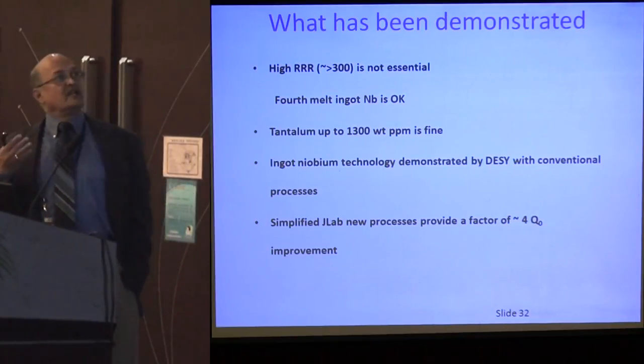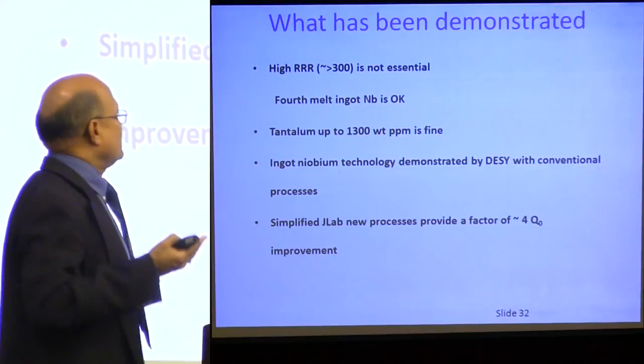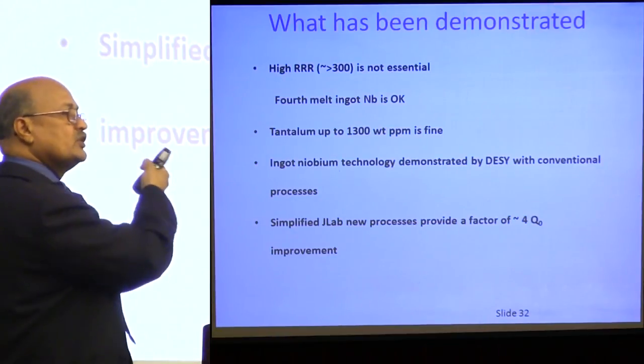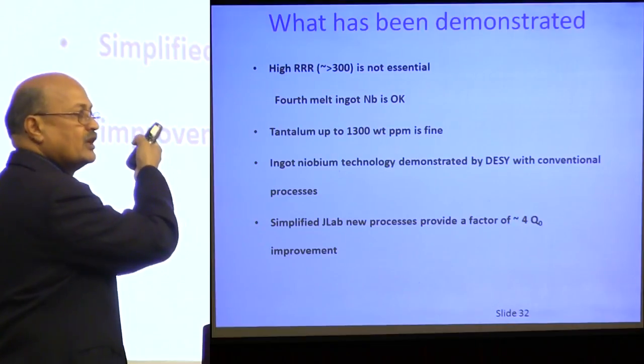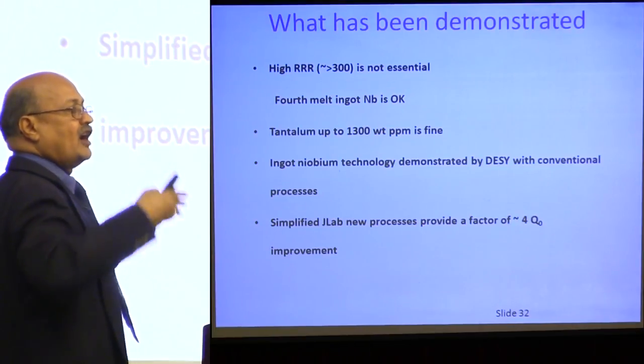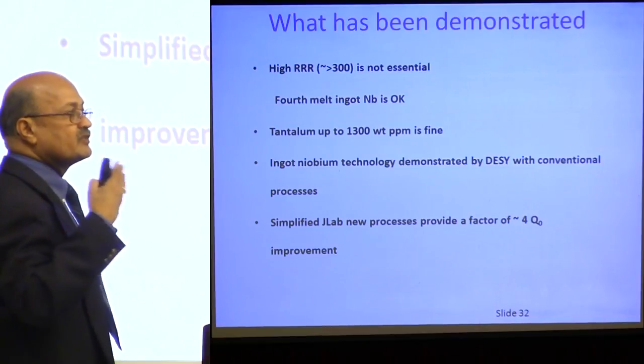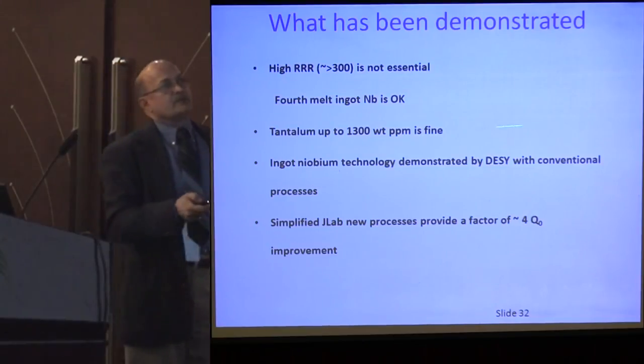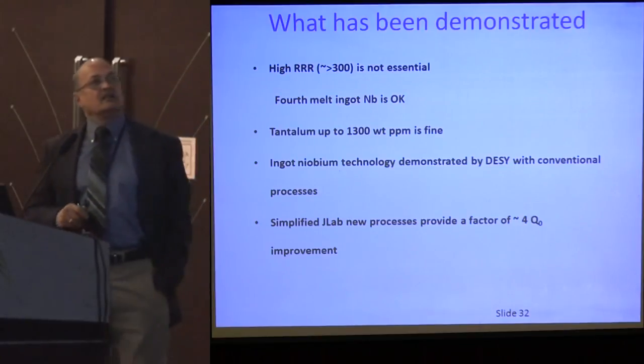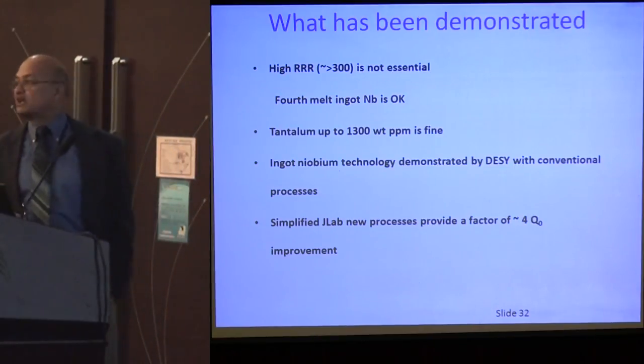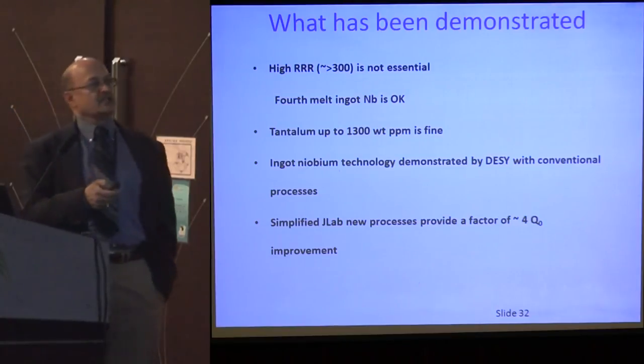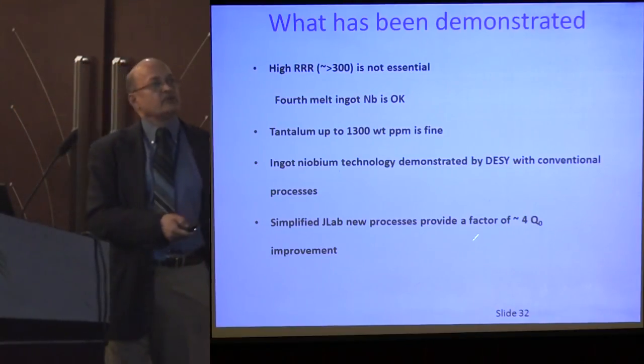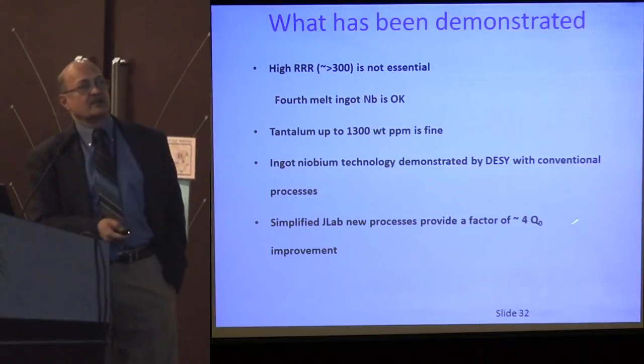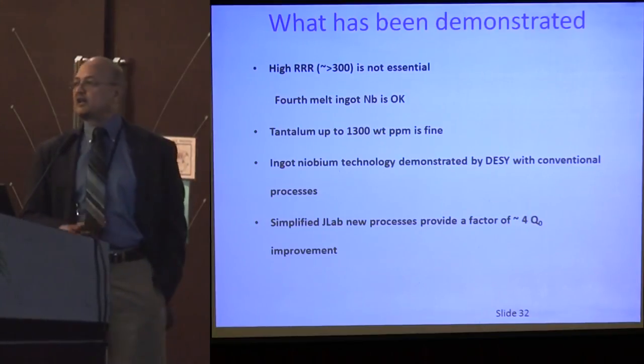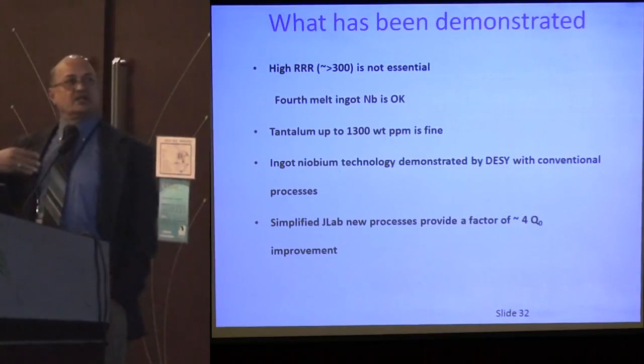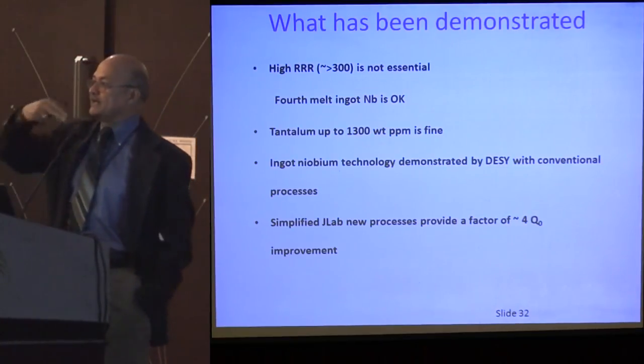The tantalum up to 1300 weight ppm is fine. It doesn't drastically affect the performance. So one could use the niobium coming from this largest pyrochlore mine, where the cost is going to be a factor of 3 different. And ingot niobium technology is actually demonstrated by DESY in Germany with conventional processes. And recently we have implemented simplified processes, and we are able to achieve a factor of 4 improvement in quality factor. That means the heat loss into the accelerator system will be reduced by that amount.